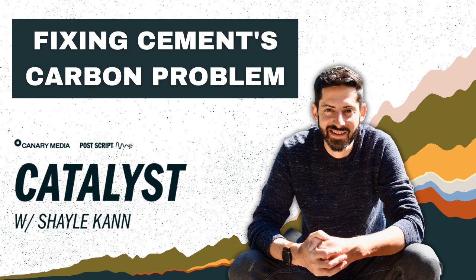Yeah, that's a fantastic question. So what you're normally blending into Portland cement are silicates. So Portland cement, as I said before, is a tricalcium silicate, which means there's 3 calciums for 1 silicate. But the hardened form of Portland cement, the phase that gives it its strength, is one calcium to 1 silicate to 1 water. So it's called CSH with a stoichiometry of approximately 1 to 1 to 1. So when you hydrate Portland cement and add water to it, you have a lot more calcium floating around than you really need. And this doesn't do you any favors from a strength and durability standpoint.